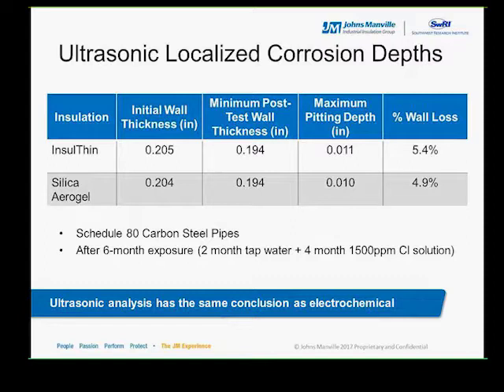That is, the corrosion resulted in about 5% loss in wall thickness at these localized points after the sweating conditions. So I want to reiterate before we leave the slide that the numbers of this table are localized corrosion depths as opposed to the mean corrosion depths that the electrochemical method calculates in the previous slide. That's one of the reasons why I kept the units different in presenting the information, essentially to act as a differentiation between the two different test methods, being the electrochemical and the ultrasonic.